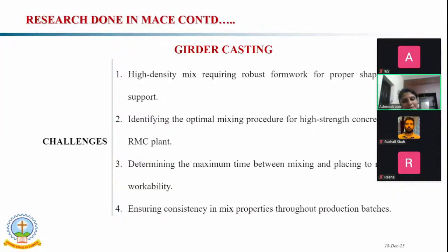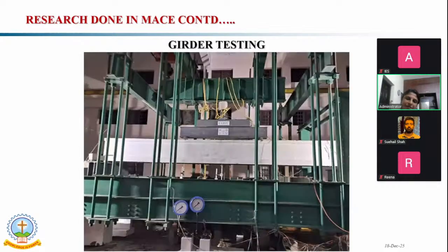So getting consistent mix properties across the production batches was the next major challenge we faced. After 28 days, we tested the girders, all four of them. We got around 700 kilonewton in the case of UHPC alone.